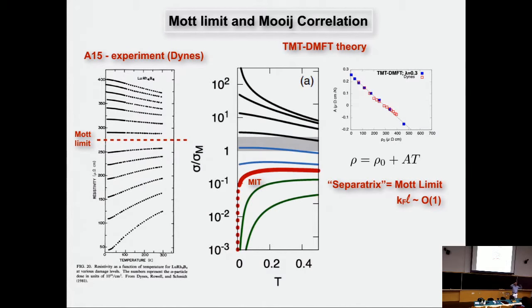No, no, this region, the Mott limit is not the metal-insulator transition. Metal-insulator transition is here. So this intermediate region, as you can see also here in the experiment, the resistivity goes up, but it's finite at low temperature. So this is not an insulator. This is just a metal with strange temperature dependence.